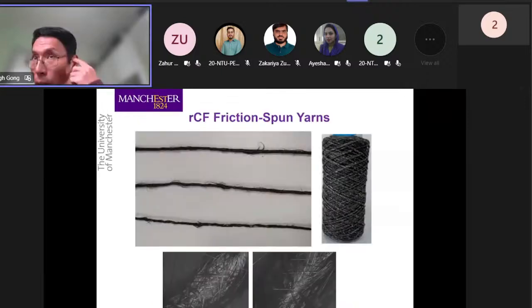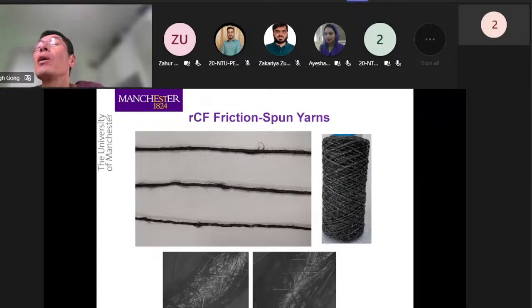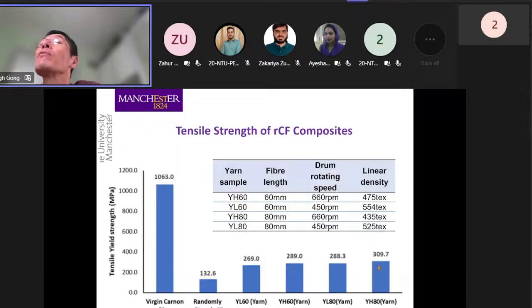And these are some yarn samples we produced. One of the issues you can see is the fiber alignment is not great. So there is still lots of work to do in terms of optimizing the process. And this is something we've carried out in terms of looking at the composites made from these yarns with different fiber length, different drum speed, and also yarn linear density.